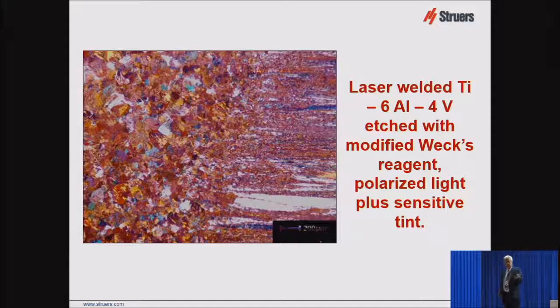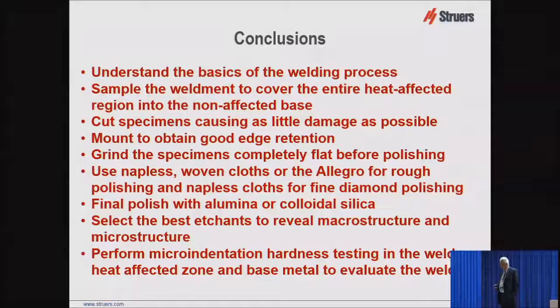And color etching titanium is very useful, just like color etching other metals and alloys. So in conclusion, we want to understand the basics of the welding process when we're doing our microscopy work so we can have a better understanding of what we're seeing and why we're seeing it. You want to sample the weldment to cover the entire heat-affected region into the non-affected base. So you want to have base metal, heat-affected zone, and weld metal to look at.